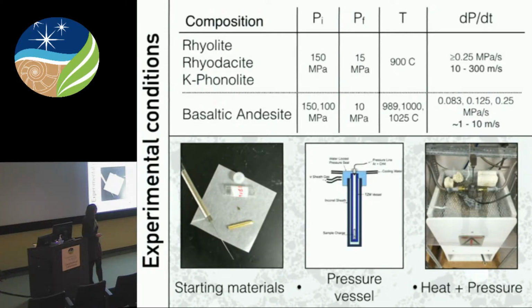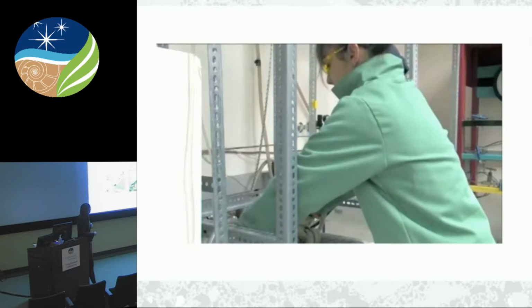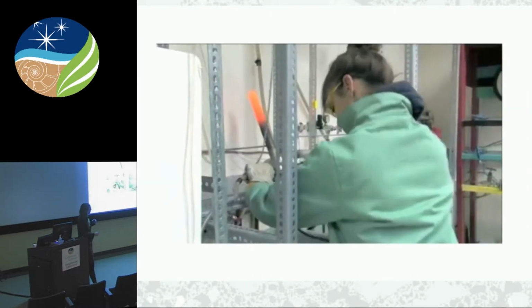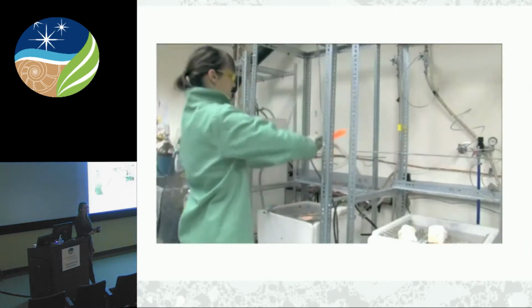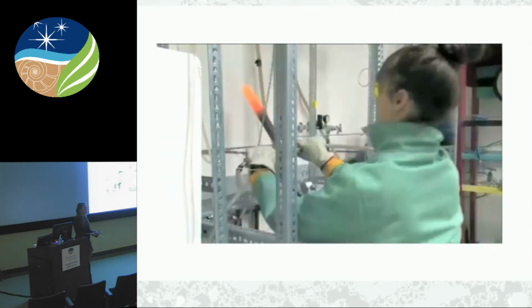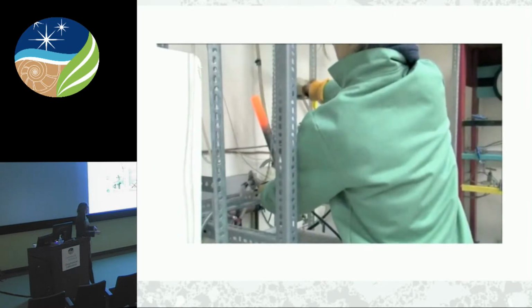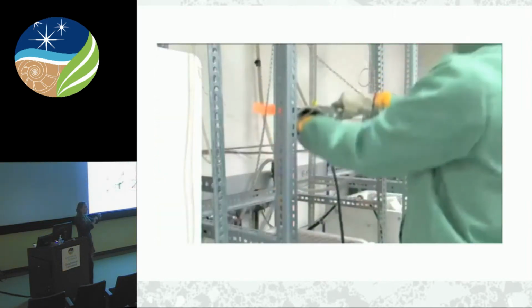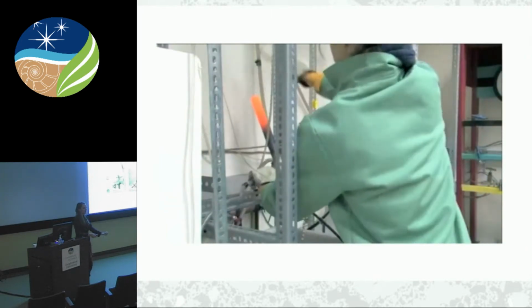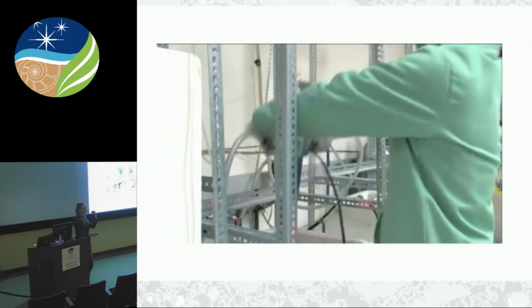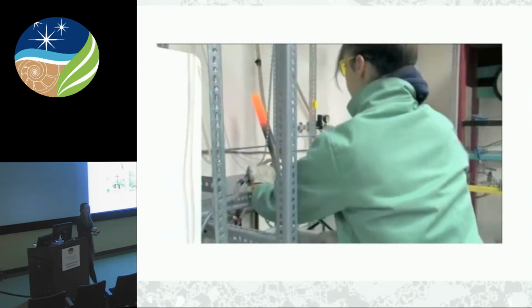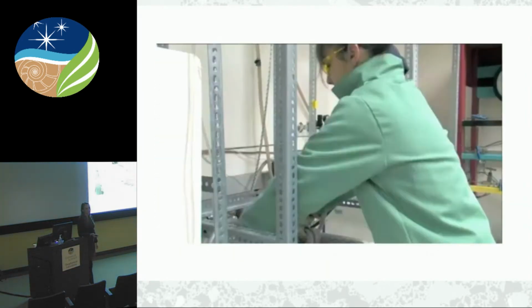And I used a few different decompression rates to also look at whether decompression rate might affect the percolation threshold as well. Now, it's this water-cooled jacket that you can kind of see poking out of the furnace here that's kind of the novelty of this experimental setup. And that's because looking at low viscosity melts, we want to try and freeze kinetic processes as soon as possible. So we need to quench the samples very quickly. And this method of pulling the experiment out and inverting it drops the sample from in the bottom of the pressure vessel into the water-cooled region. And that allows us to cool our sample to the glass transition between about 2 and 6 seconds.